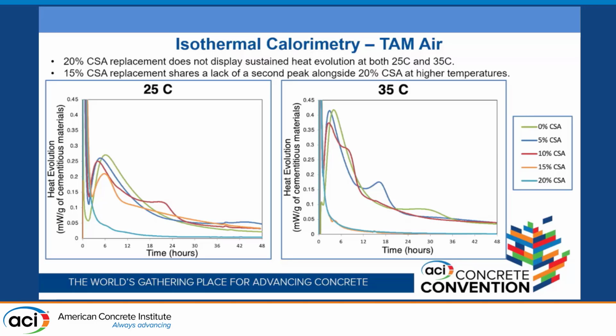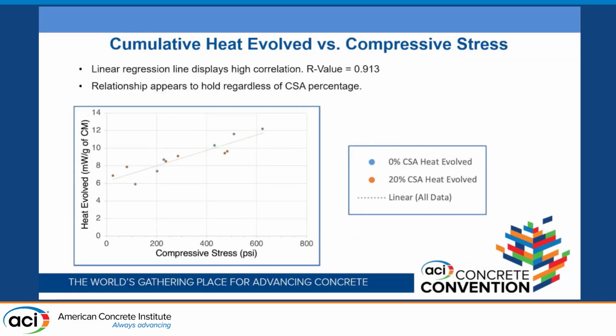So, with that being said, we then conducted a set of very early age compressive stress tests to compare the actual relationship between 2 of the data types that we've been collecting. So we looked at cumulative heat evolved and compressive stress and looked at the relationship between the 2 and saw that there was a high correlation with an R value of 0.913, and that is a strong indicator that the actual